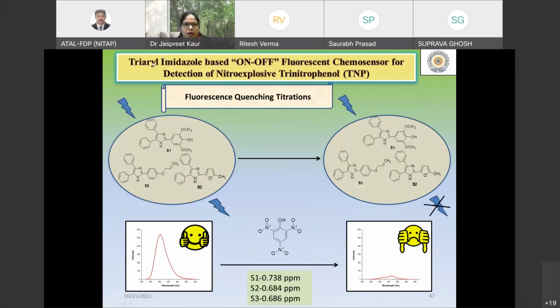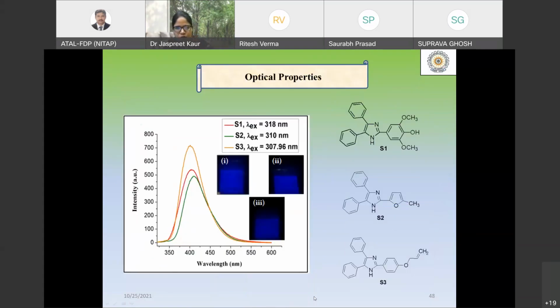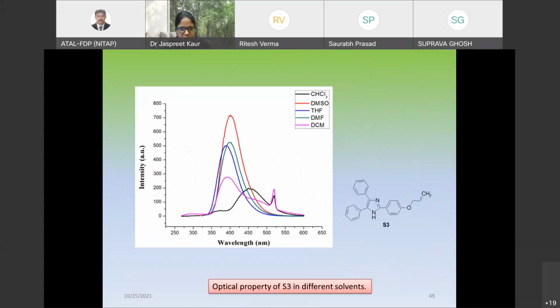So these triaryl imidazoles show on-off fluorescent chemosensing for the detection of TNP, trinitrophenol. You can see the limit of detection over here. For S1, it is 0.738 parts per million. For sample 2, it is 0.684 parts per million, and for sample 3, it is 0.686 parts per million. So for the optical properties, you can get the lambda excitation over here. This is the optical property of the S3 sample in different types of solvents. It showed maximum fluorescence in DMSO.